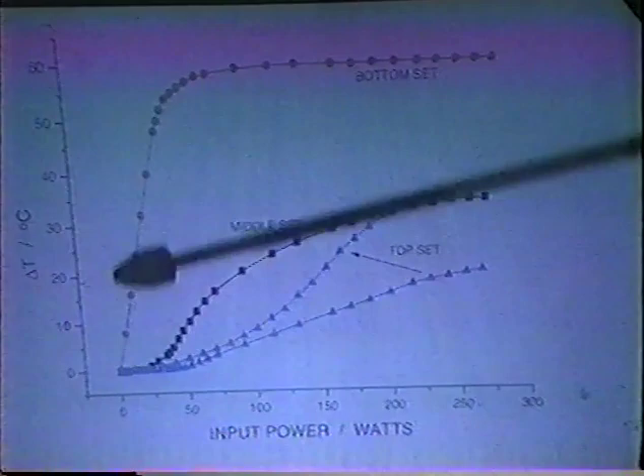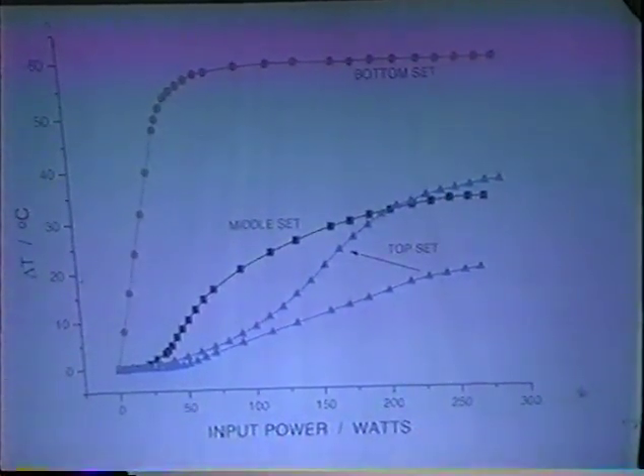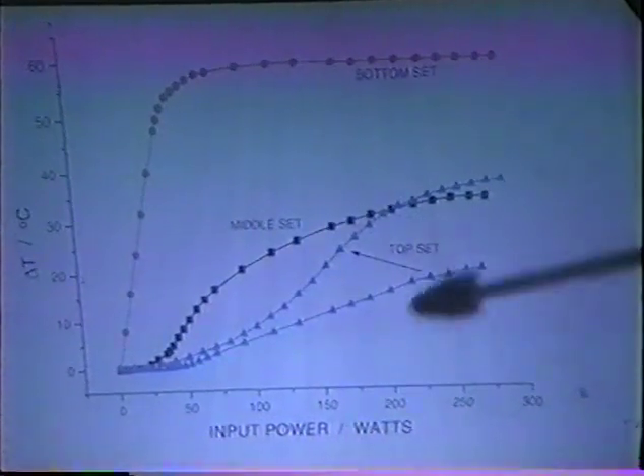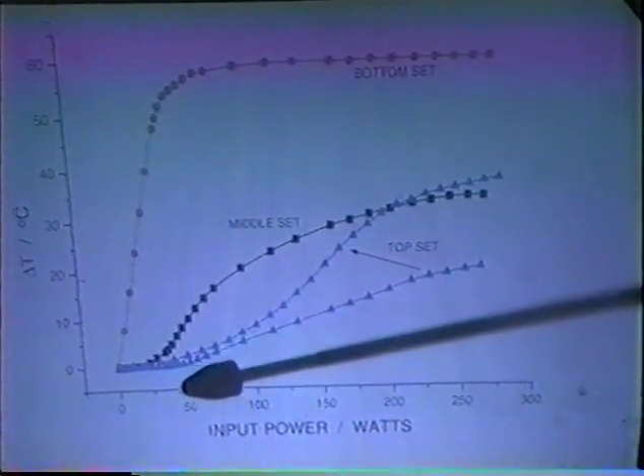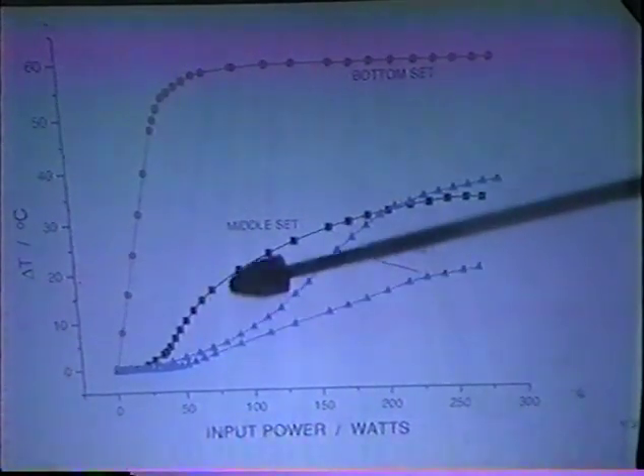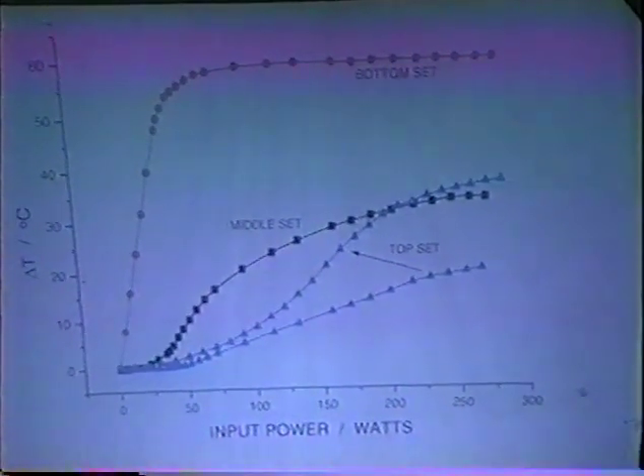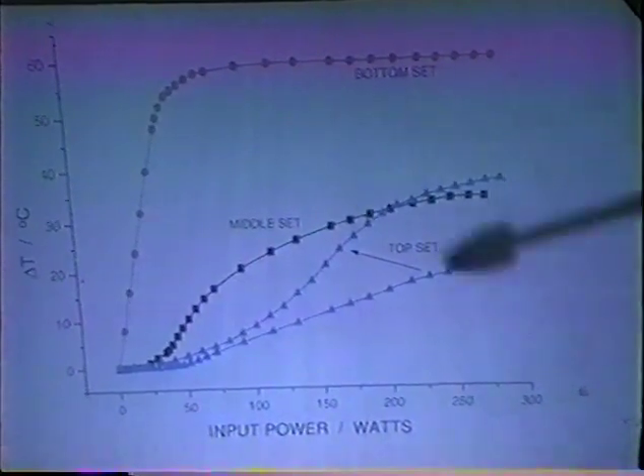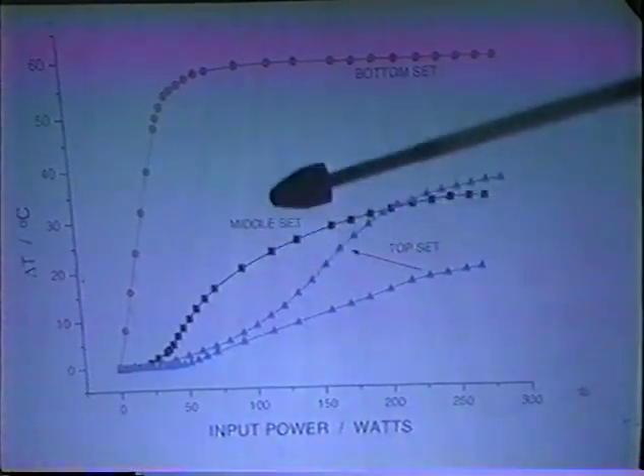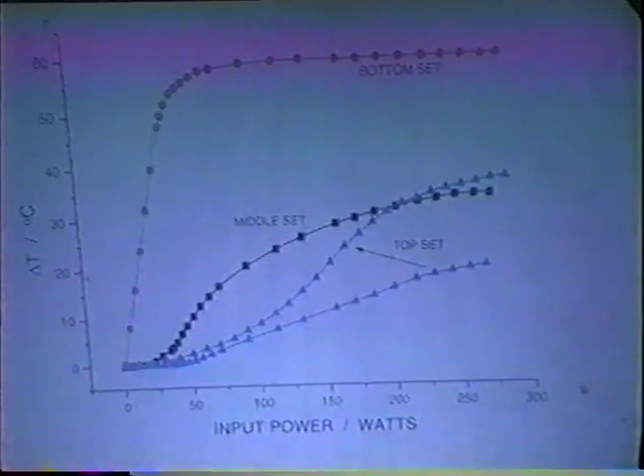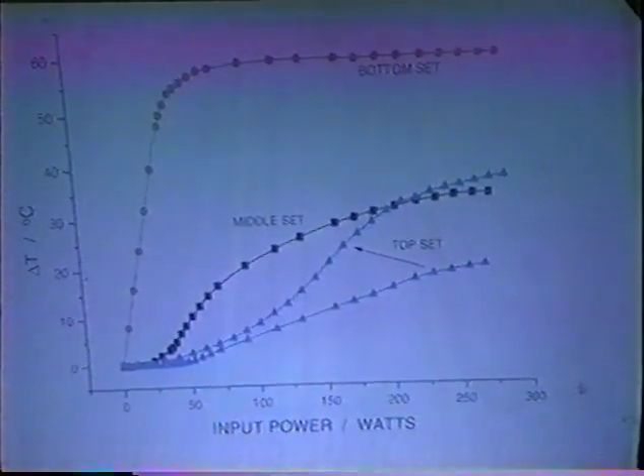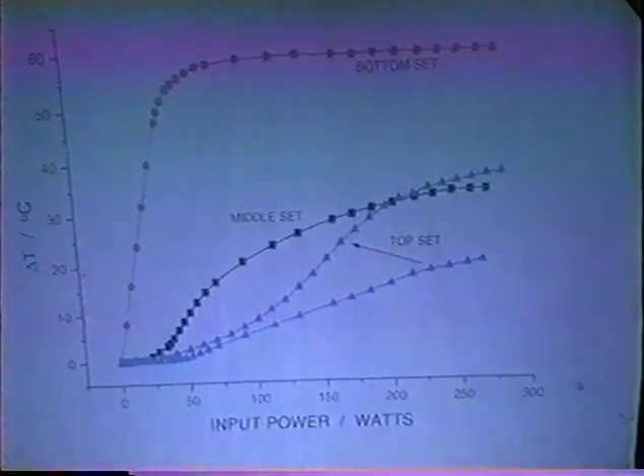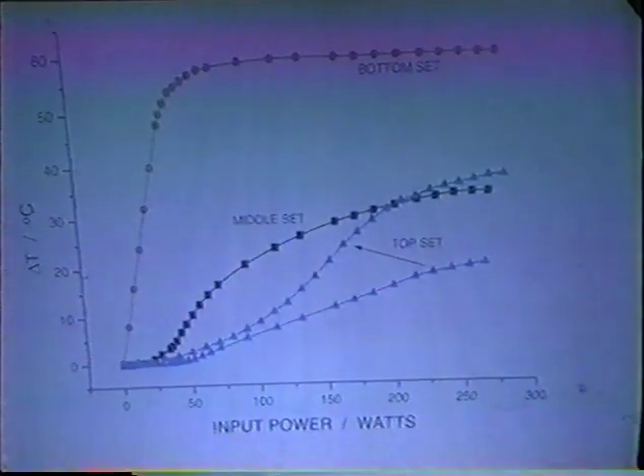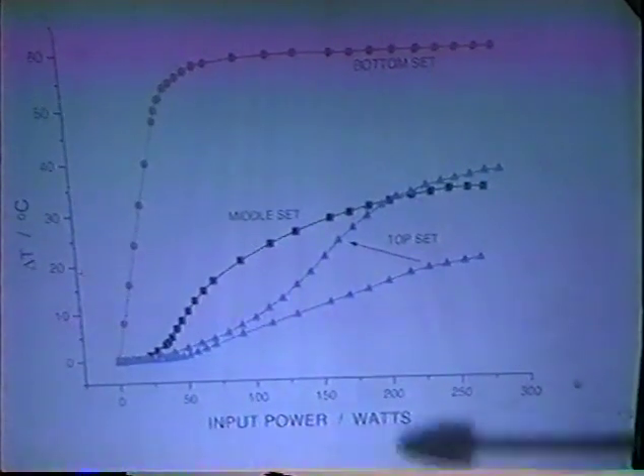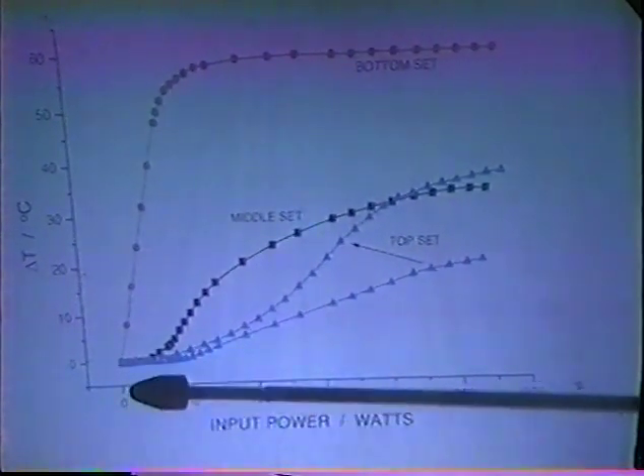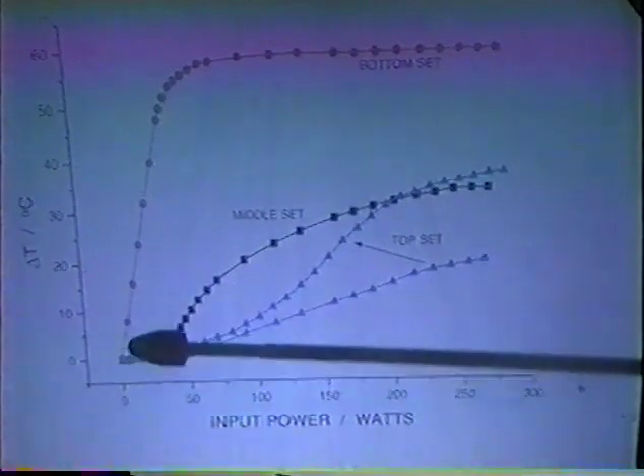So we will have a bottom set of thermistors which are located in the reaction section of the cell on the bottom. Typically we run a minimum of 2 thermistors, one located about a fourth of the way up the upper section of the calorimeter. So you have an internal and an external thermistor pair there, so we measure the temperature difference. And then at the very top, which is very high up in the cell, then you will have a third set of measuring thermistors.